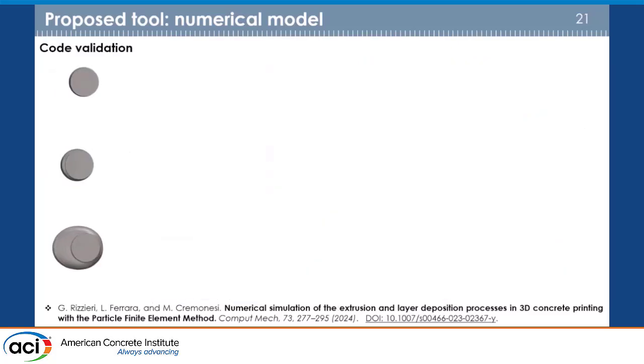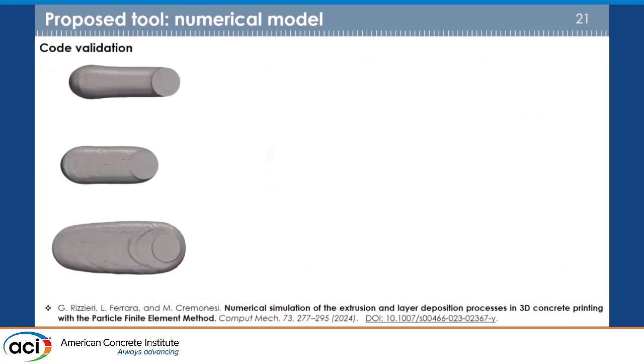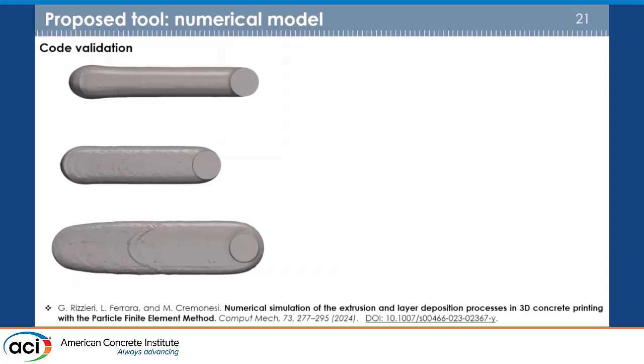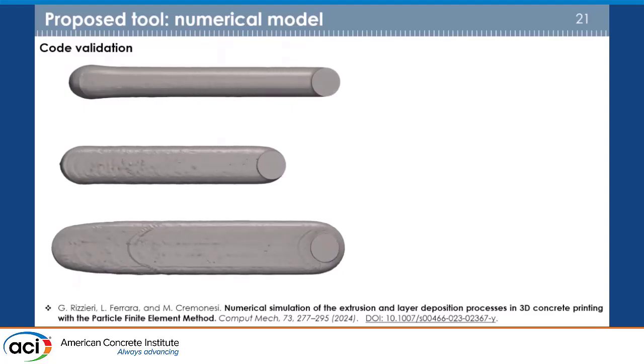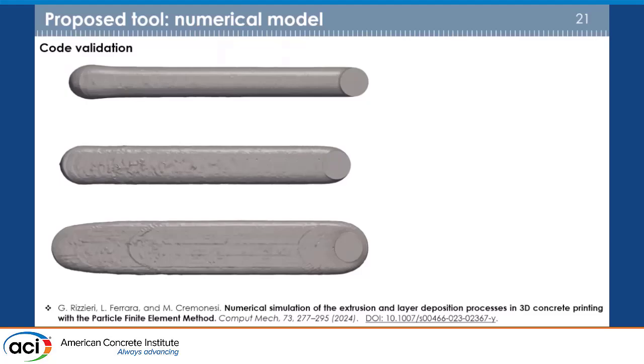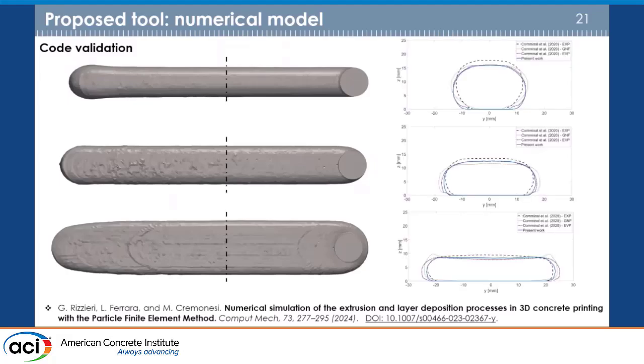We calibrated and validated with some of our own results and some from the literature. You can see here some printing processes varying the print velocity and varying the yield stress, and you can also see that if you print too close, for example, to the surface, you have a flattening of the filament deposition, and the comparison between the modeled and the predicted result is here.